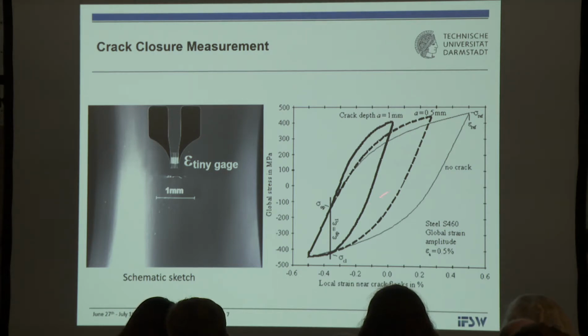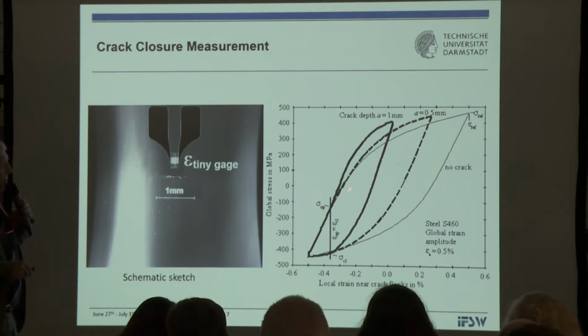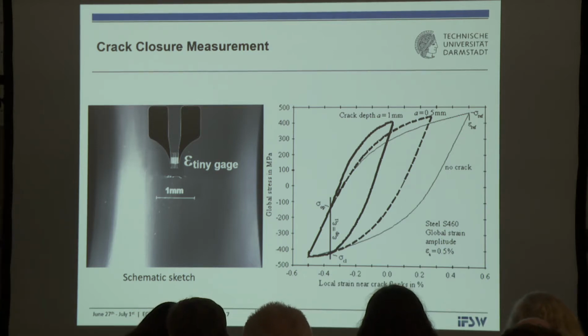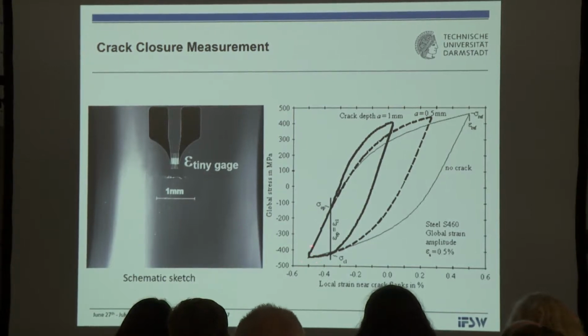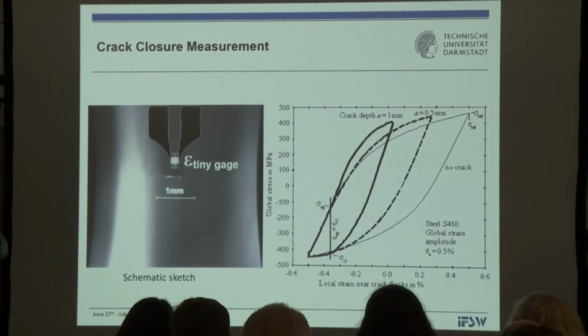On the right hand side, without a crack you would produce a conventional hysteresis loop. However, if you have a crack growing, these hysteresis loops deform, especially in the tensile half of a cycle. The strains measured by this tiny gauge become smaller and smaller the larger the crack grows. In the compressive half of the cycles, this lower reversal point remains unchanged, as if no crack were there.